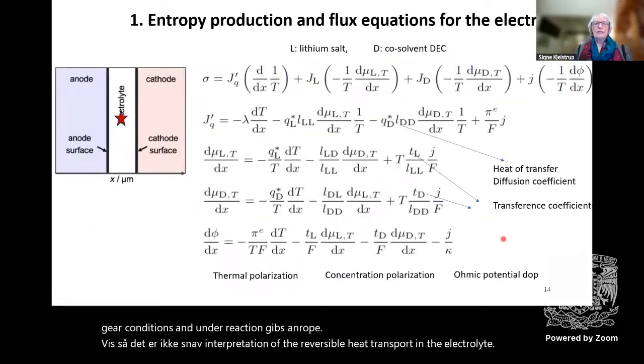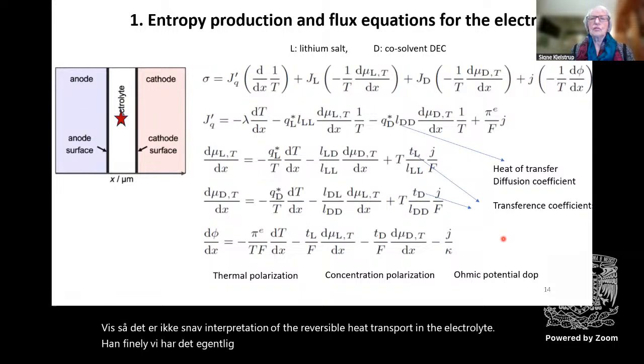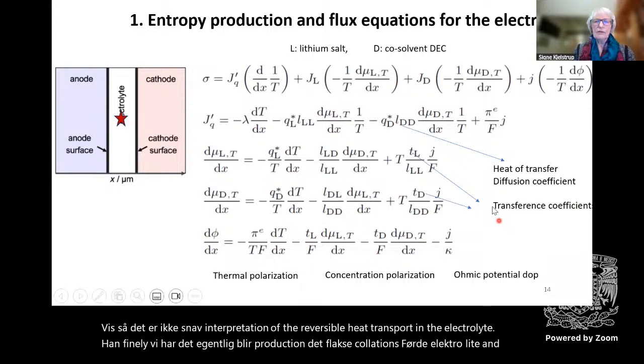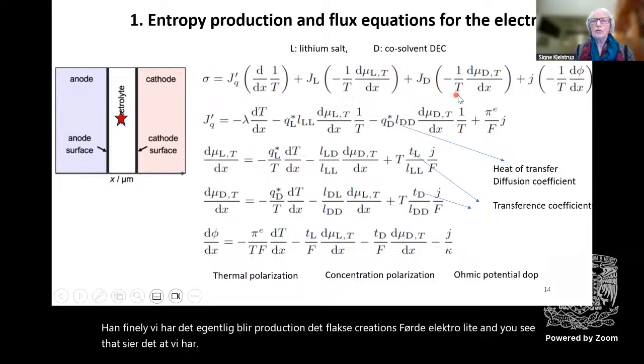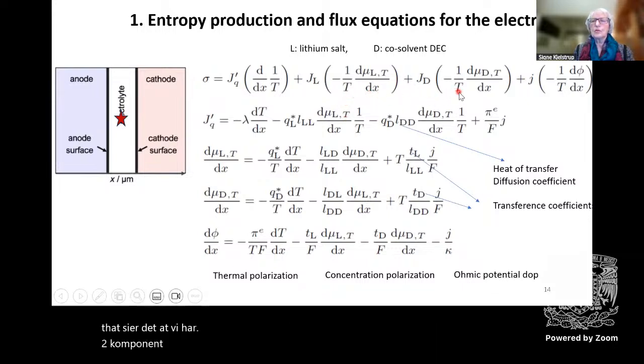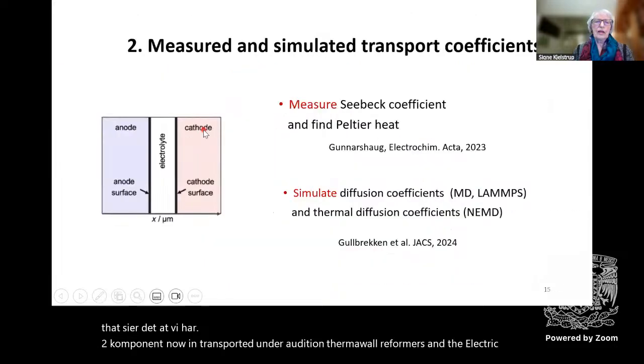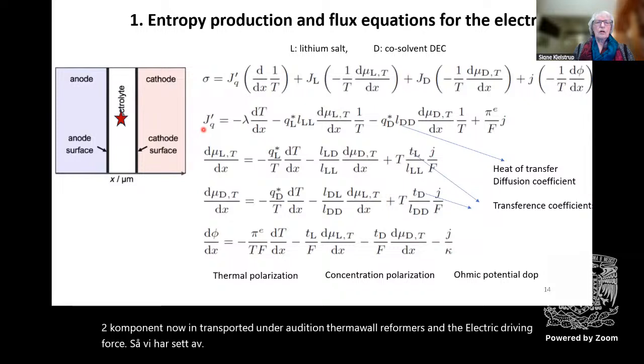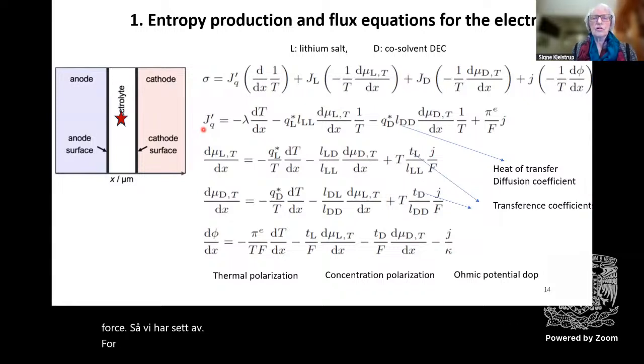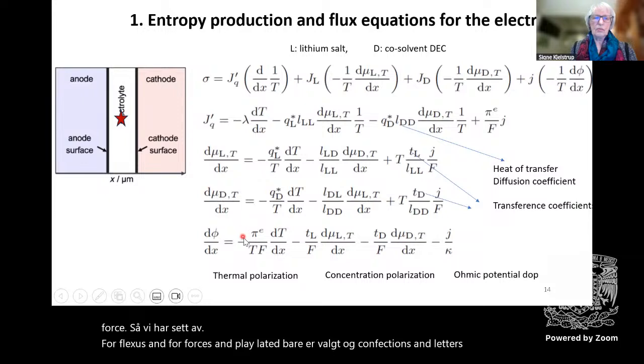And finally, we have the entropy production and the flux equations for the electrolyte. And you see that we have two components now being transported, in addition to the thermal driving force and the electric driving force. So we have a set of 4 fluxes and 4 forces, and they are related by a lot of coefficients. And let us only look at the bottom line here.